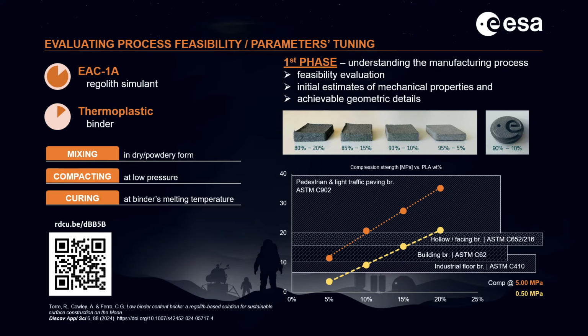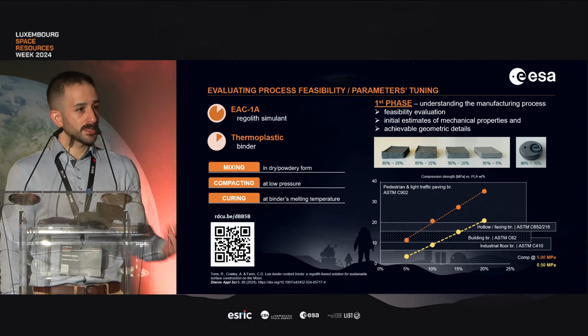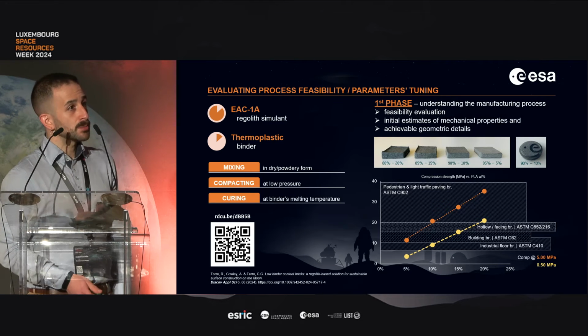The graph you see on the bottom shows the trend of the compression strength of some of these bricks with PLA against the binder weight percentage. And you can see that by playing with it and also by playing with the compaction pressure, we can cover a wide range of compression strengths, which perfectly overlap with the properties that we need on Earth for industrial floor bricks, building bricks, etc. So it seemed quite promising.